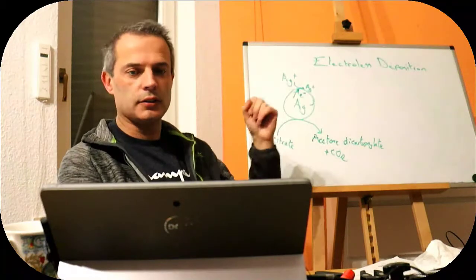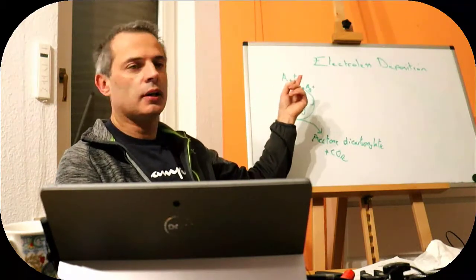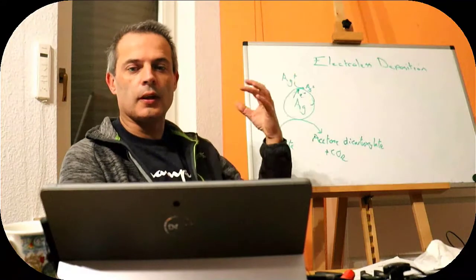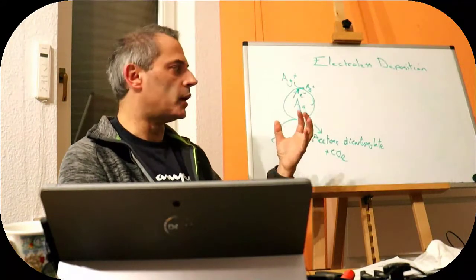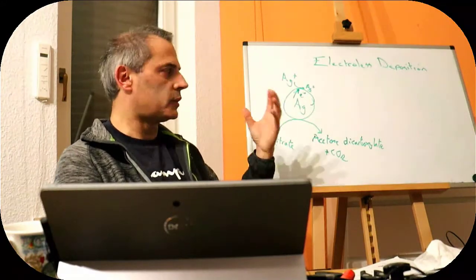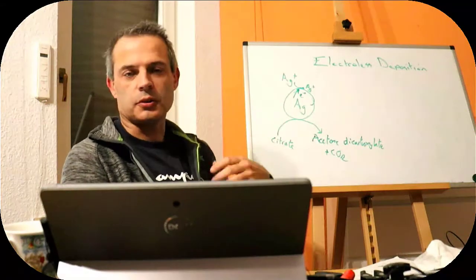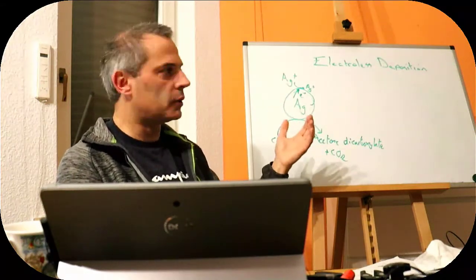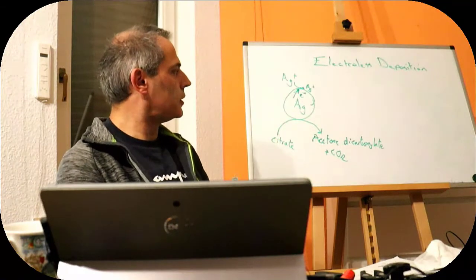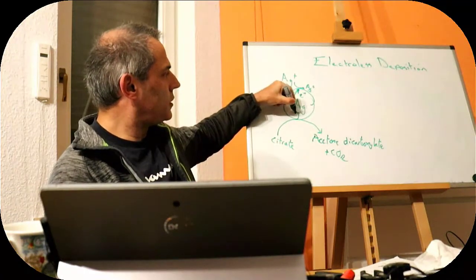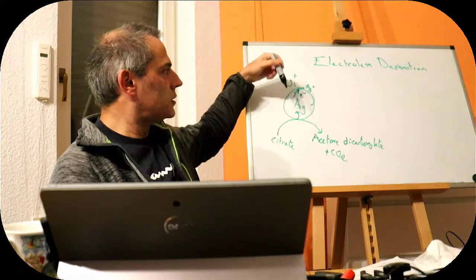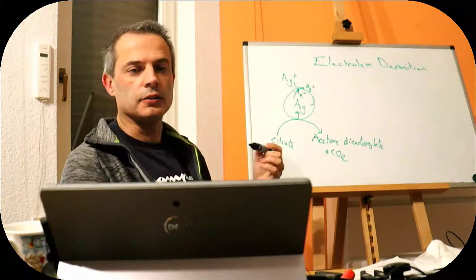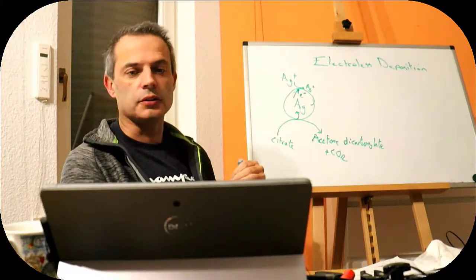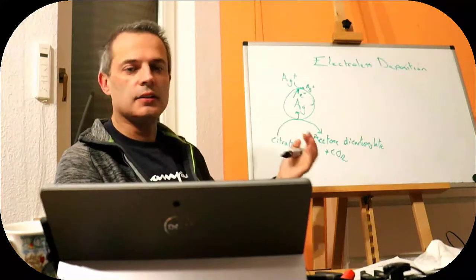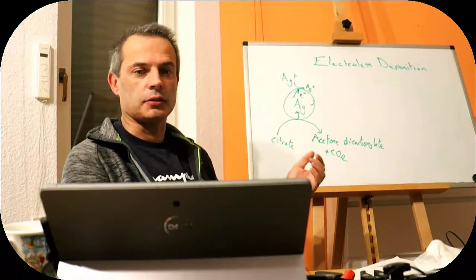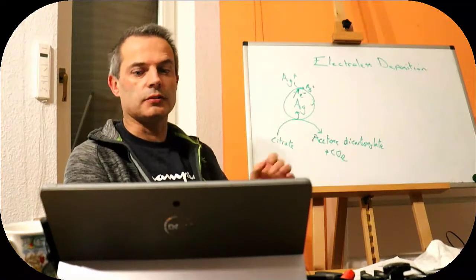And in another place on our silver particle, silver is reduced. You can see that this is very much the same as corrosion, but it's going in the other direction, and it's also the same as a normal electrochemical cell. We've got electrons flowing out of the citrate through the metal and into the silver, making the silver into silver zero, which causes a silver particle to grow. This is exactly what we want to happen at our surface, and we might even do it with silver.